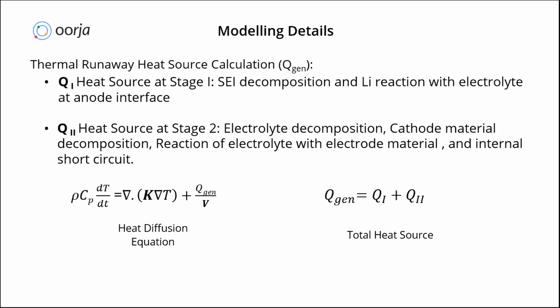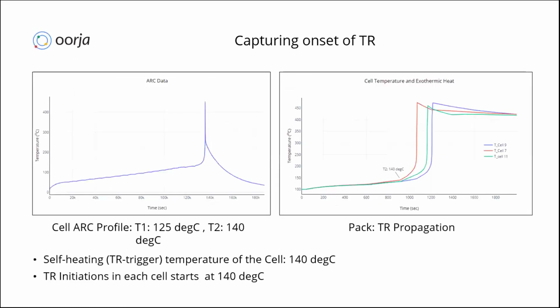At the T2 temperature, additional exothermic reactions will start happening, as mentioned over here, like electrolyte decomposition, internal short circuiting, etc. And because of that, uncontrollable heat will get released by the cell itself, due to which the cell will get into thermal runaway. So as you can see, the total heat source because of the thermal runaway is a combination of the stage 1 and the stage 2 reactions itself. And by using this total heat source, we will be solving the heat diffusion equation inside oorja.